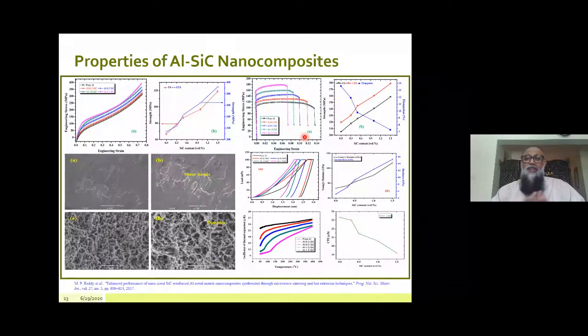The reason is that there are many factors that contribute. The main reason is the dispersion hardening phenomenon, because the presence of hard particles in the matrix impedes the movement of dislocations. That is why the strength is improved. Secondly, through the rule of mixtures, we are adding hard particles into the soft matrix, and with the increasing amount of hard particles, the strength will naturally improve. Also, besides these two factors, the presence of ceramic particles also increases the load bearing capacity of the aluminum matrix. That is why we have seen an increase in mechanical properties with increasing amount of silicon carbide nanoparticles in the matrix.